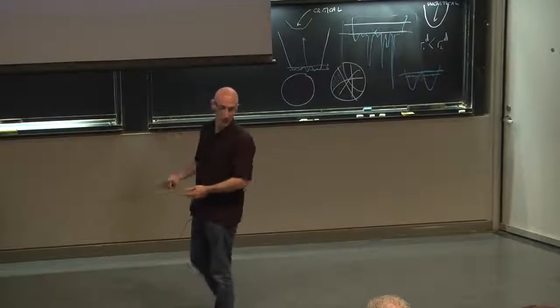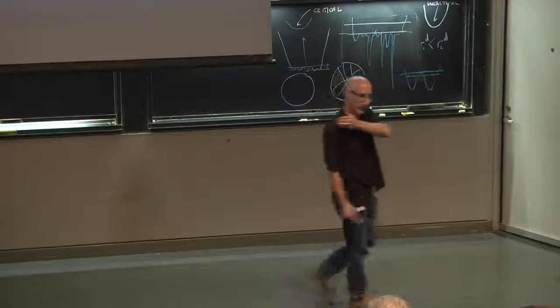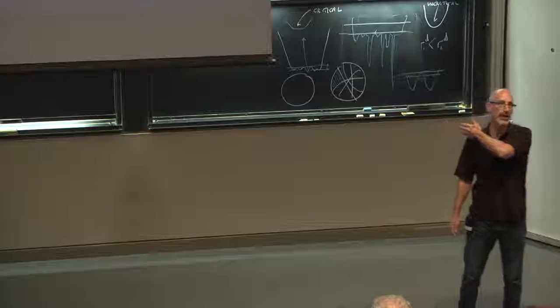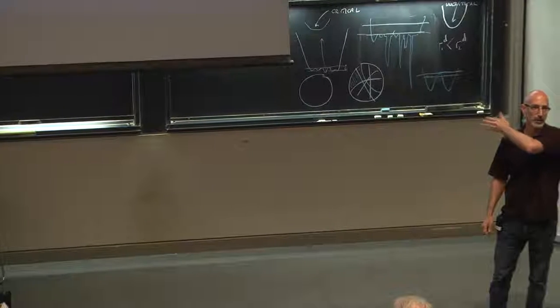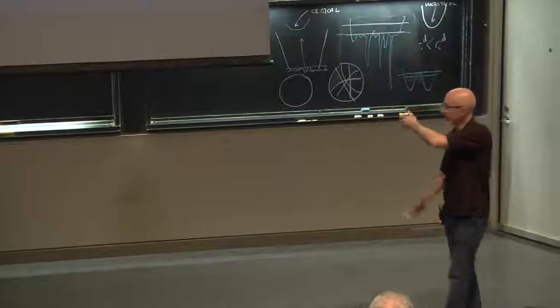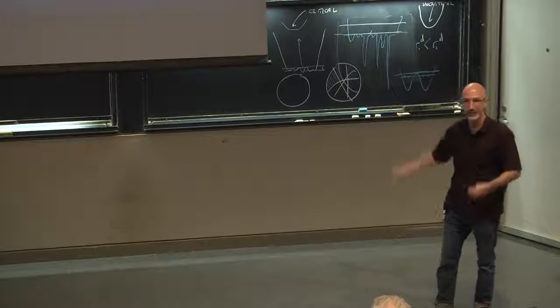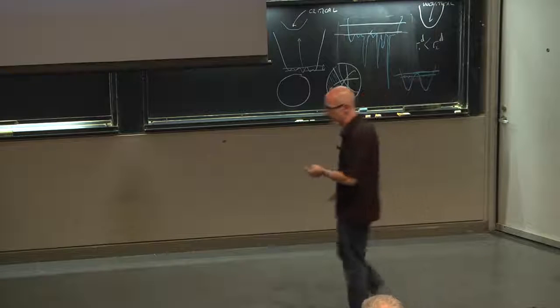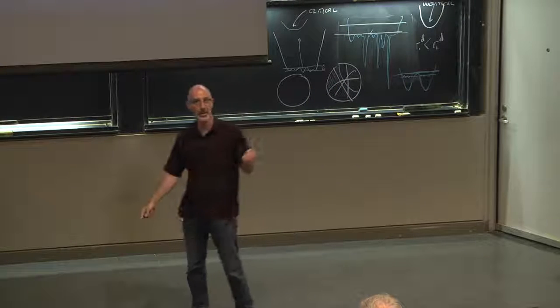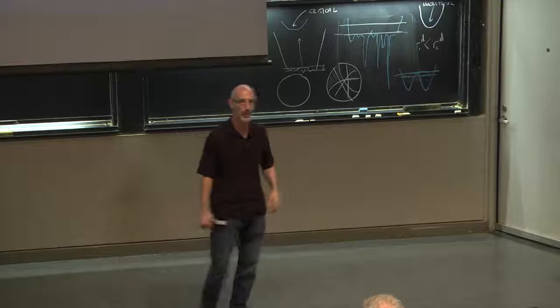But this is not going to work, right? This is exactly what I said doesn't show you anything in a supercooled liquid. If you do this for the static configurations, and this is, let's say, the density of the liquid, then this is just the static structure factor, the kind of thing you would measure in neutron scattering, and you see nothing as the system is being cooled down.